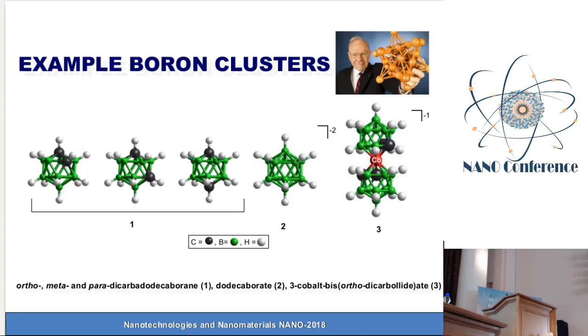The best known example of boron clusters is the dodecaborate anion, which contains 12 boron atoms and 12 hydrogen atoms linked to the borons. The BH groups in such a cluster can be replaced by various heteroatoms, very often by carbons, and after replacement of two BH groups by two CH groups, dicarbadodecaboranes are obtained. They exist in three different isomers, depending upon the mutual location of the carbon atoms: ortho, meta, and para isomers, and they differ in properties.